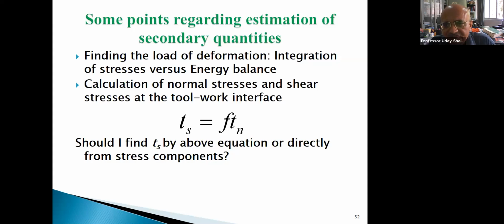You integrate the stresses on the surface. The other way is that you can find out the total power dissipated. And then once the power is known, then power divided by velocity, because the punch is giving all the power. It is compressing; all that upper die is coming and compressing the forging material. So you can say force into velocity is equal to power. So you can find out the forces by means of the integration of stresses, and also you can find out by energy balance. Now which approach will give good result?